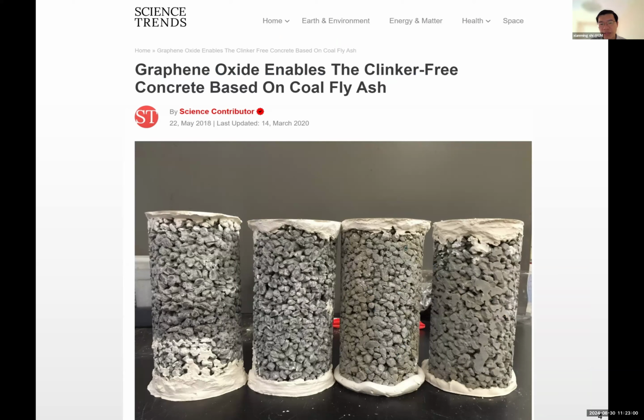So starting from the first topic, graphene oxide enables clinker-free concrete based on coal fly ash. As you can see, we made some concrete cylinders in the lab. The two on the left were made with ordinary Portland cement. The two on the right were made with coal ash without any cement clinker. The color is slightly different. Other than that, most behaviors are pretty much comparable, in terms of mechanical properties and durability, as you will see later.